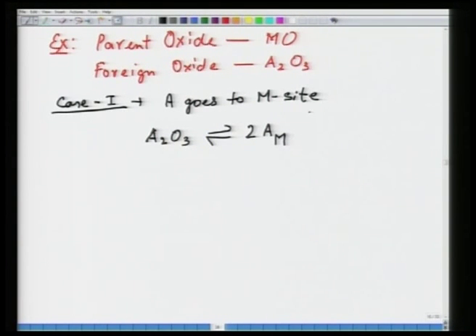Now both of the A's have gone to M site, what it means is that the valence of A is plus 3, valence of M is plus 2, as a result the A, which is going to M site, is going to have extra plus 1 charge, which is denoted by a dot. So, 2 AM dot plus, let us say, since 2 A's are going to 2 M sites, to maintain the site and mass balance, 2 of the 3 oxygens here go to oxygen site. So, they maintain the site balance of MO, which is the parent lattice. Extra oxygen goes out, half O2. So, extra oxygen does not stay inside.